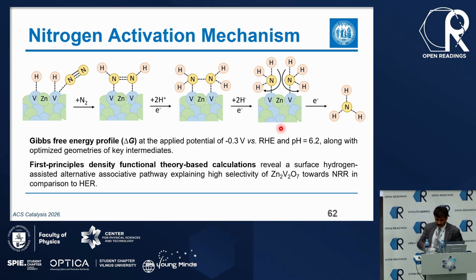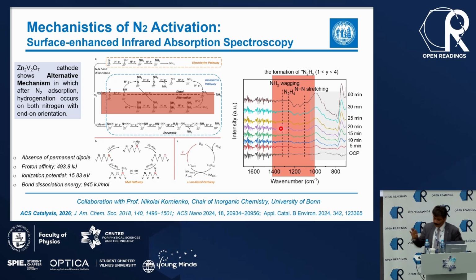We did a very detailed study, so in the interest of time, it is published in ACS Catalysis 2026, so it's a recent paper. Because on the surface, it's always a challenge. If you publish a paper, people say, how do you know this? So surface enhanced infrared, which is called SEIRAS, tells you what species are formed. Now this is one way. What we see is that once you have this catalyst, it's becoming saturated at some point. And that's the problem with most of the catalysts. They are saturated at some point. And how do you go around?